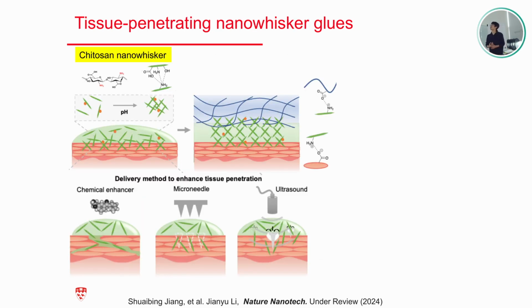So how we can overcome this issue and make a really better nanoparticle glue is the following. Our proposal is, first of all, we need to overcome these two limitations. In terms of the tissue barrier effect, we need to allow the nanoparticle to penetrate through the tissue. In this case, we propose to use ultrasound as a strategy to deploy the nanoparticle through, or we can use other approaches, like a physical approach using microneedles to pierce the tissue and get the particles over. Or we can use a chemical approach, where you treat the skin with some chemical and it can peel off or loosen the skin matrix. With all of that, we can achieve tissue penetration. And for the second issue, the weak interaction between the nanoparticle and the polymer, we propose the use of this nano whiskers glue.